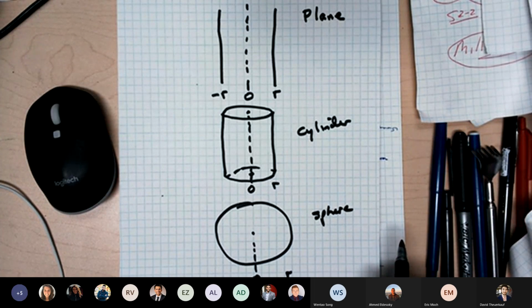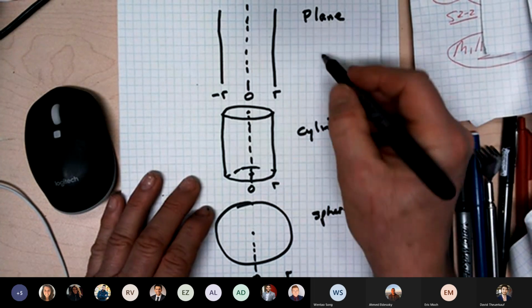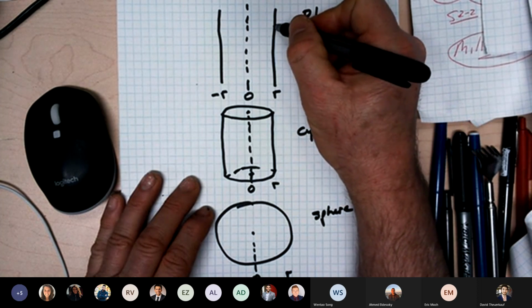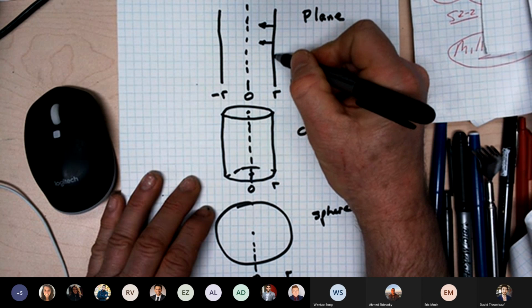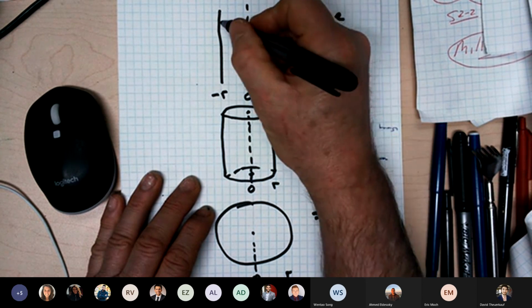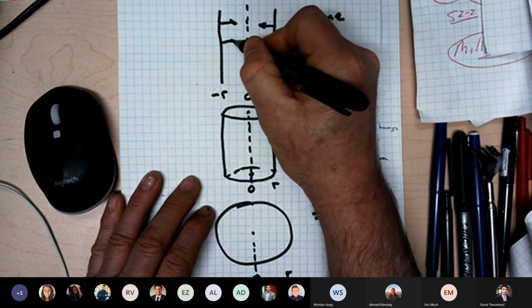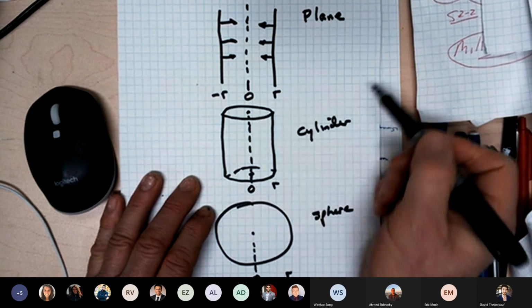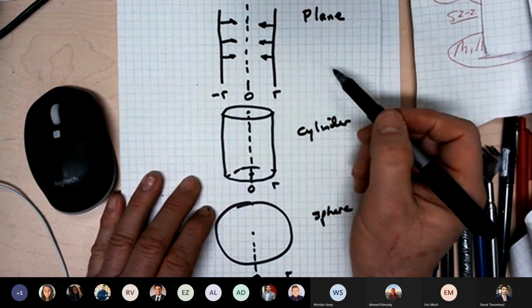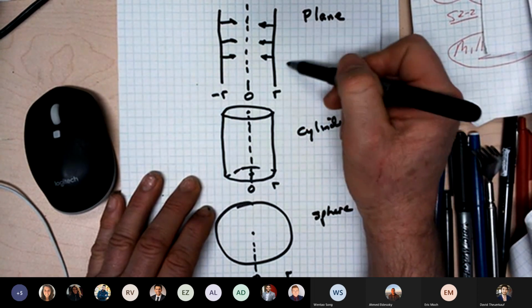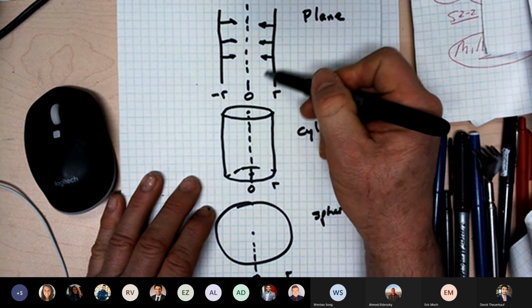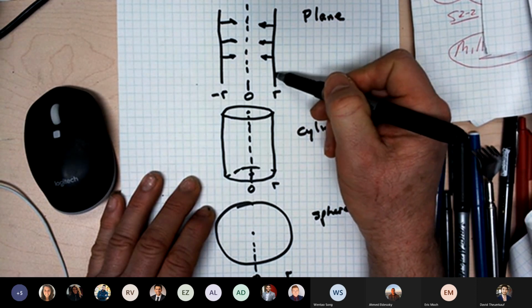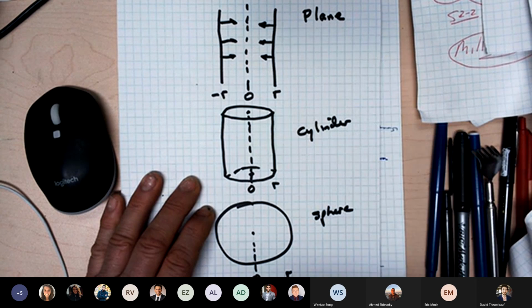And these differ in that, for the case of the plane, the lithium diffusion is toward the center from both sides, and it's in one dimension. The lithium ions come from the surface, they diffuse to the center. There's no reason for them to diffuse at some strange angle, just by the symmetry of the situation.